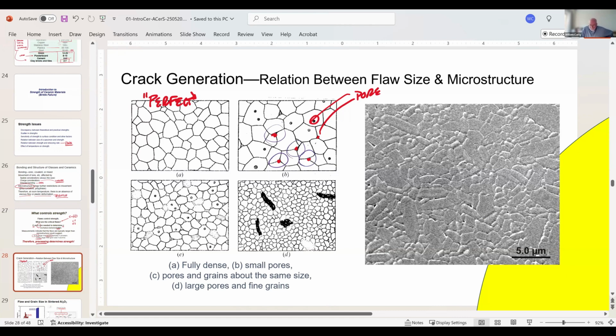I can have a microstructure where I have large pores that are stuck in the middle, or a second phase in the system. And then I have very large pores that are several grains large, that are basically big holes in the system. To give you an example, ceramic microstructure on the right, and these pores here that you see that are kind of triangular shaped, these pores tend to be potentially a problem. Here's one, for example.